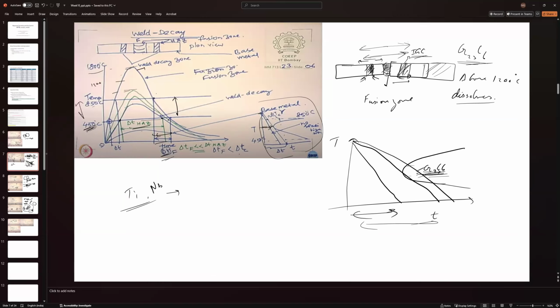So if you remember this plot, it's your sensitization. If you have higher carbon content, this is highest carbon content. And as you're moving this way, this is lower, this is lowest carbon content. This one is the most susceptible to IGC. So this would still apply in this weld decay. Increasing carbon content would not help. Really.